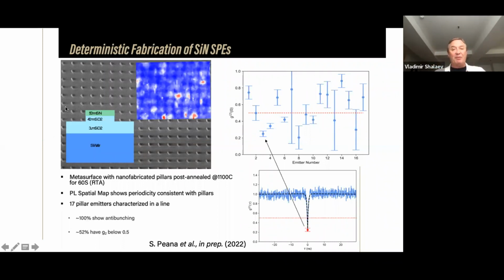Here we just picked arbitrary 17 pillars in a row, and all of them show anti-bunching, all 100%. And actually more than 50% have g2 going below 0.5. It's actually very important because all other ways of creating single photon emitters are statistical, like implantation or annealing.